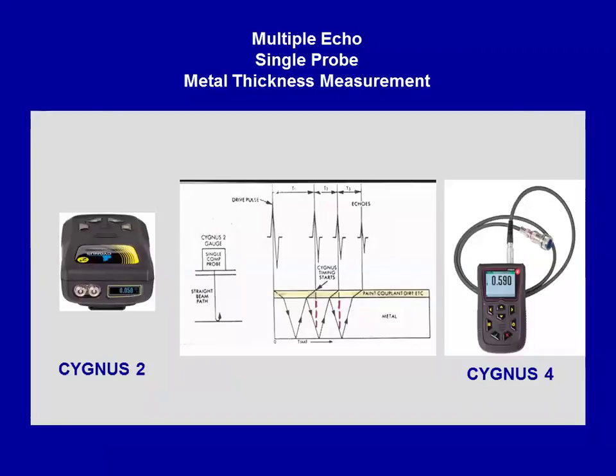So what we do now, we spread this out for time. We're not V-beams. We're a straight up and down sound beam. The sound goes into the steel and reverberates within the steel until it loses energy and goes away. So we put the sound into the metal, and we wait for the first echo to come back, and that's the one that turns our clock on.